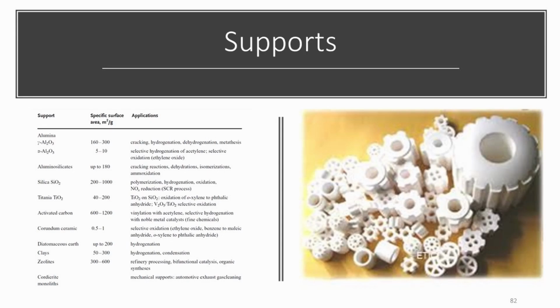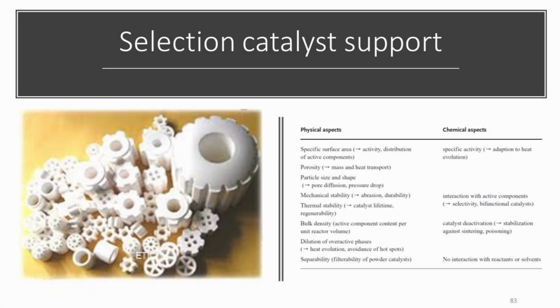The choice of either a silica or alumina support depends on the specific application and the metals that will be deposited. Silica has a low point of zero charge and it is difficult to deposit metals like gold. Alumina generally has the highest mechanical robustness as well as the highest thermal stability, especially when heated in the presence of steam. However, especially in the case of gamma alumina, it does show a high reactivity with certain metals, especially bivalent metal cations that can easily be inserted into empty octahedral positions in the structure.